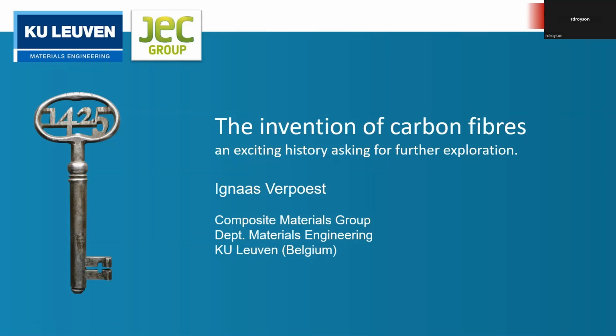Yeah. I must admit I have only been reading bits and pieces of reports on lignin fibers, so I will give a rather superficial impression. These attempts to make carbon fibers out of lignin are not new. Lignin has a very high carbon content, so it's evident that you could make carbon fibers out of it. But lignin has also a very, very complex molecular structure, much more complex than polyacrylonitrile, which is more or less a linear polymer, and you can orient it very well during the production of polyacrylonitrile filaments. And then you reconstruct that into a very well-oriented graphitic structure.